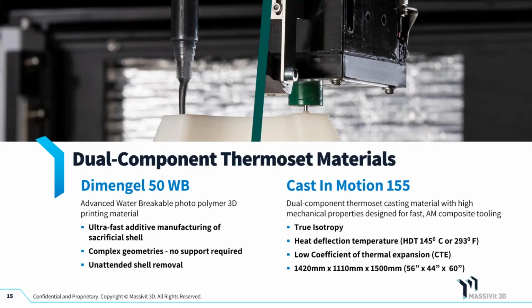On the other side is the Cast in Motion 155, or now we call it the CIM 500. It has a heat deflection temperature of 145 degrees C, just under 300 degrees F, and it has a fairly low coefficient of thermal expansion. I know that's kind of ambiguous, but it's close to aluminum. It's around 25 parts per million for the CTE, and it's truly isotropic. We've had it tested by a third-party organization, and it's an isotropic mold. So the thermal expansion in the X, Y, and Z are exactly the same. The tensile strength under compression is the same in X, Y, and Z. And it's something that hasn't been done in 3D printing.